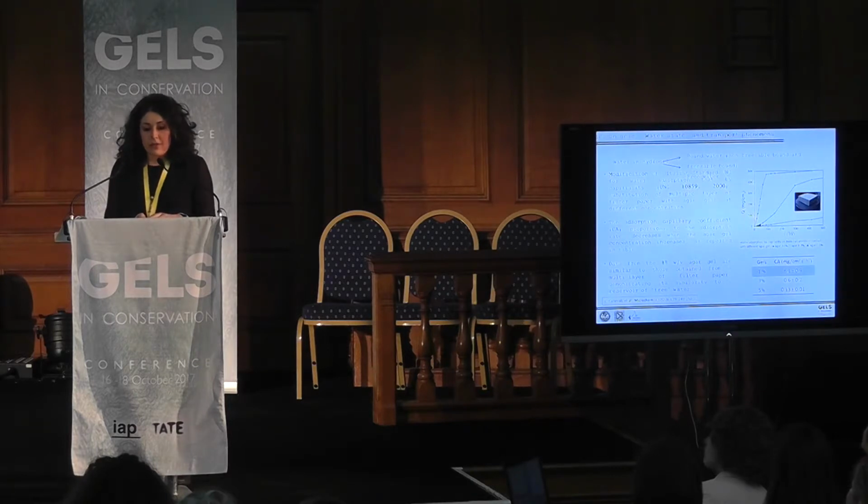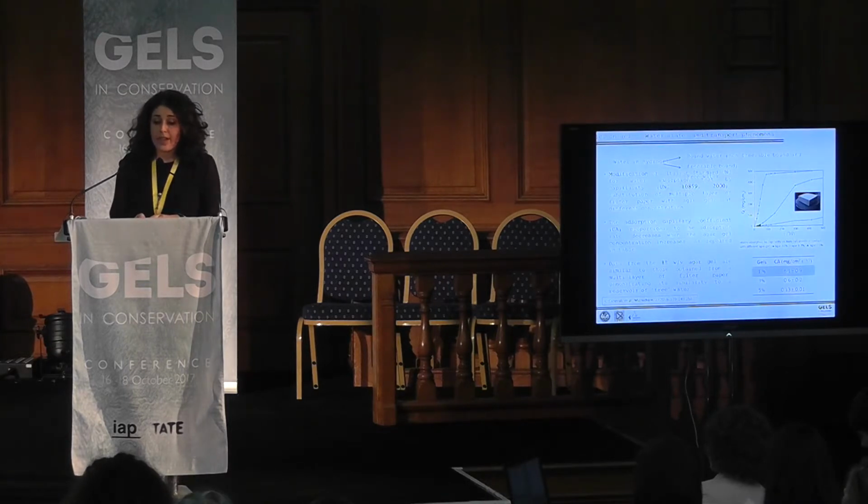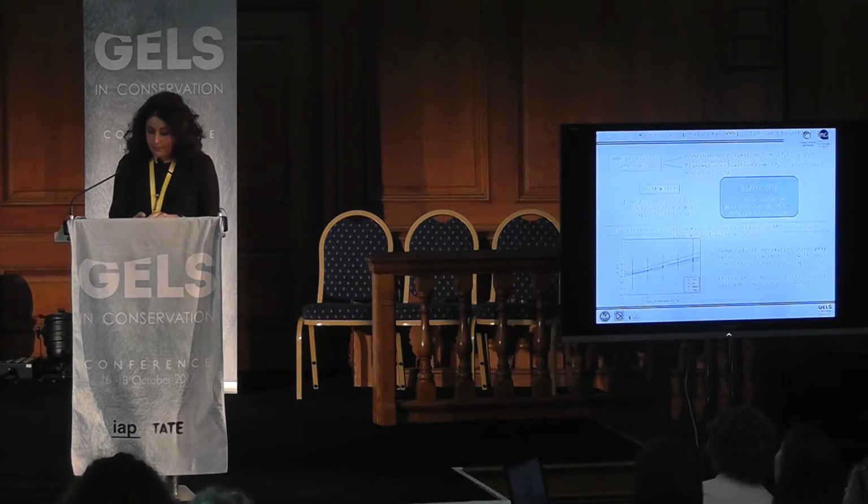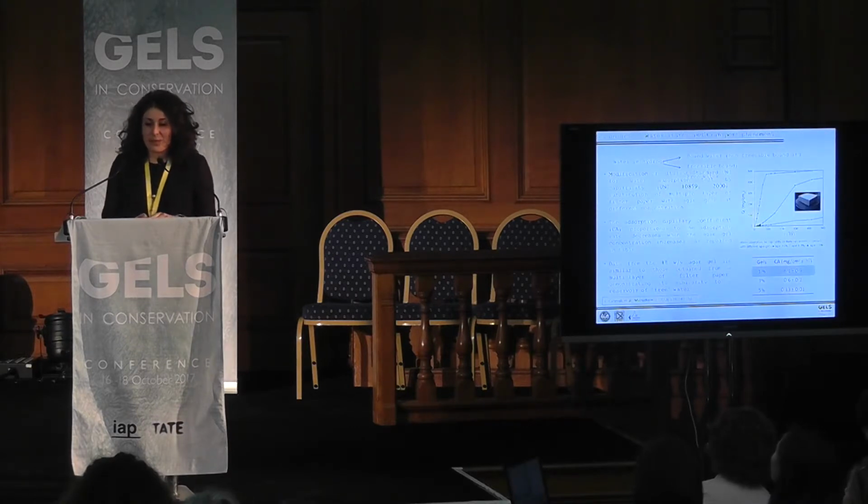As you can see from the graph and the table, increasing the concentration of agar gel, we find a decrease of the absorption capillarity coefficient. Moreover, we noticed that the agar at 1% weight on volume exhibits a trend similar to that we can record with a multi-filter paper. So we can say that the agar gel at 1% weight on volume is like a source of free water.